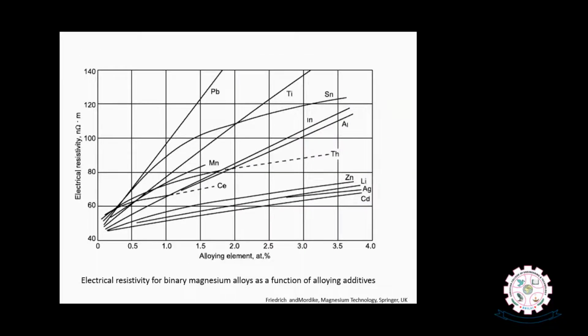So most of the cast structures, if you observe the microstructure of the cast magnesium alloys, since the solubility limit of the alloying elements is very minute, limited to less than 1% or less than 2% at room temperature, if we add more amount of alloying elements, certainly this addition will result in development of intermetallic phases, which we see presenting at the grain boundaries.